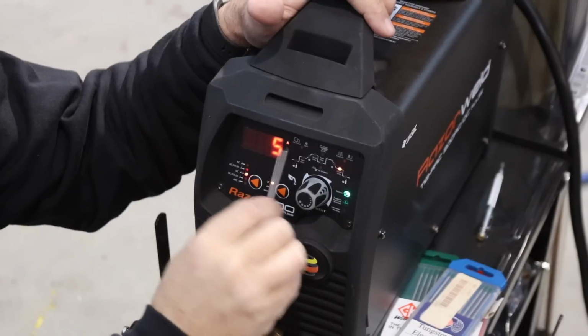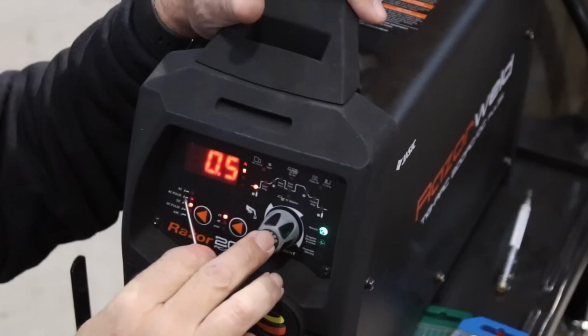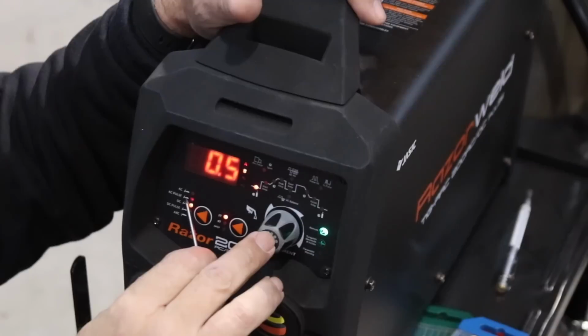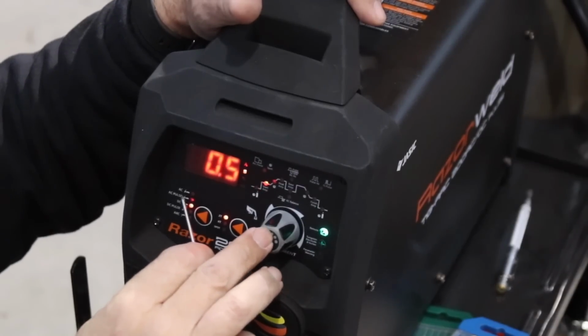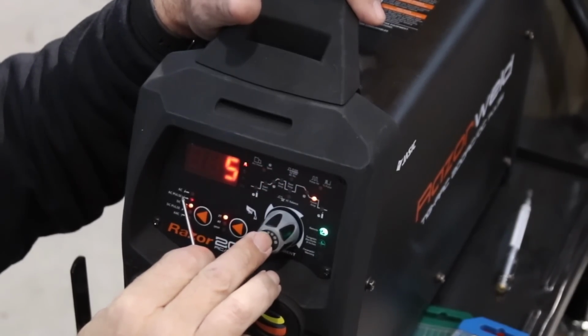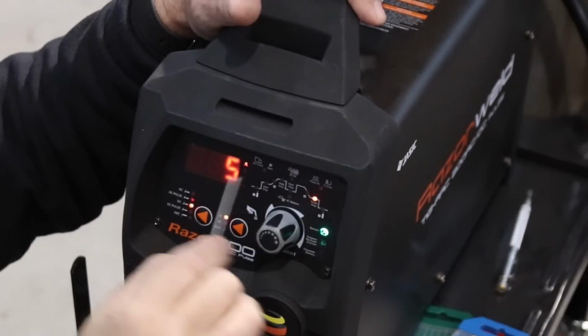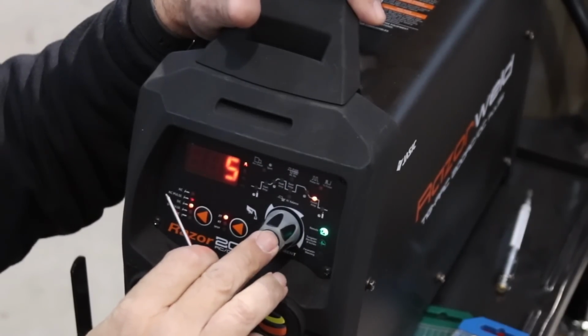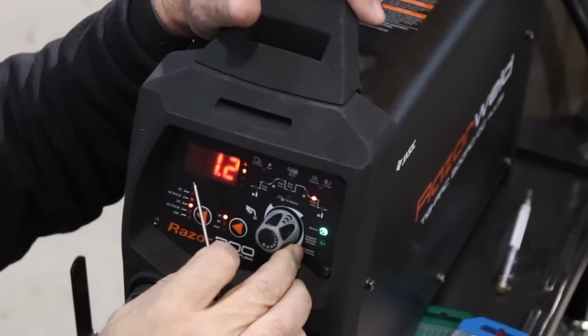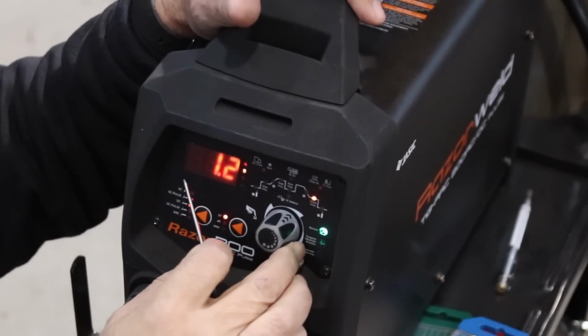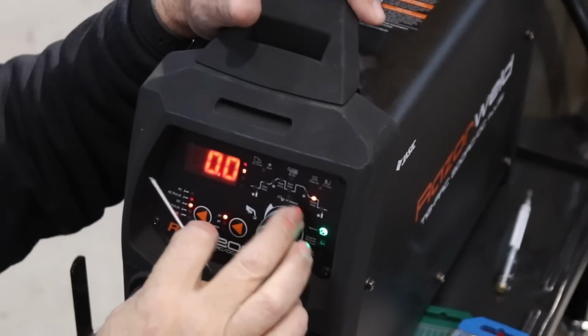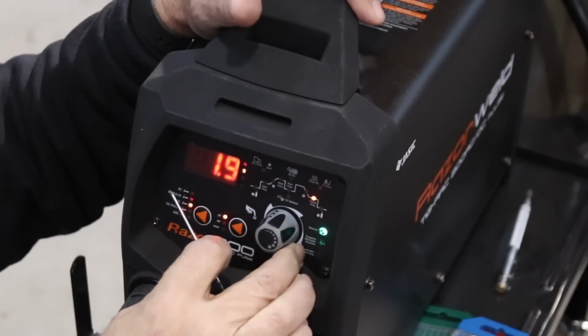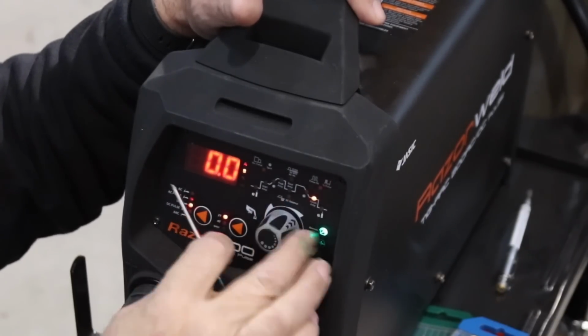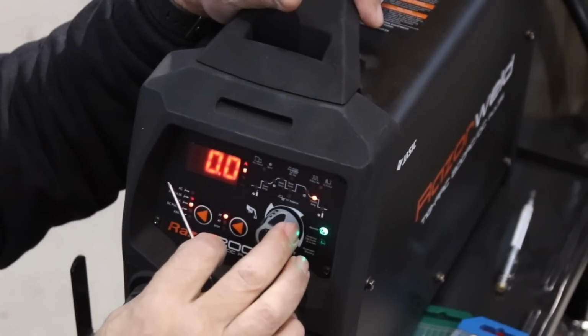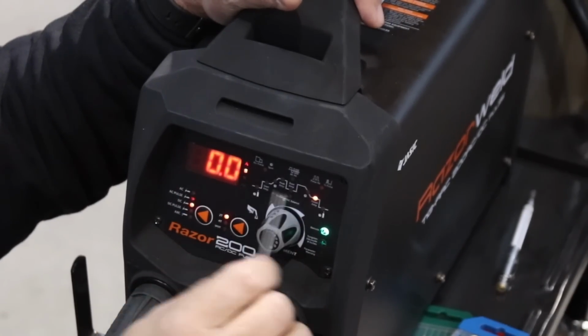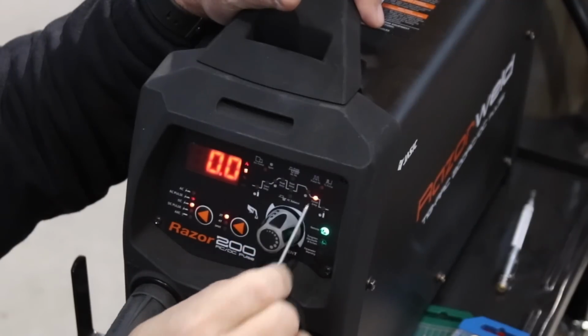Finish amps, again, depends on the thickness you're welding. It's amperage and time. So when I get to finish amps, 5 amps, I can also have it hold 5 amps for however many seconds before it turns off. For most operations you won't even need to do that. Once it gets to 5 amps, you'd want it to just turn off. But it is an option. So you have amperage and time there at the finish.